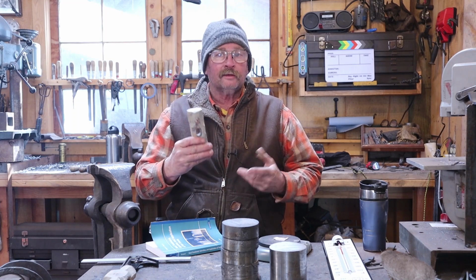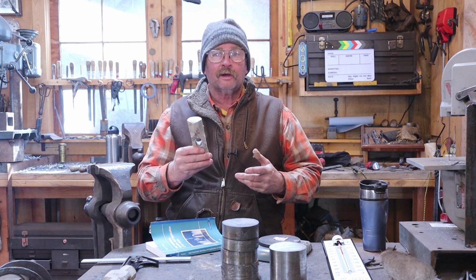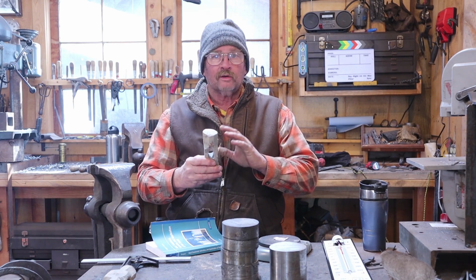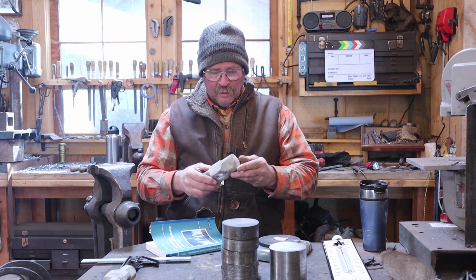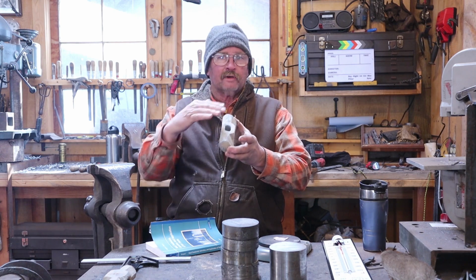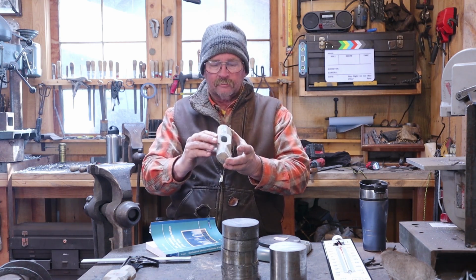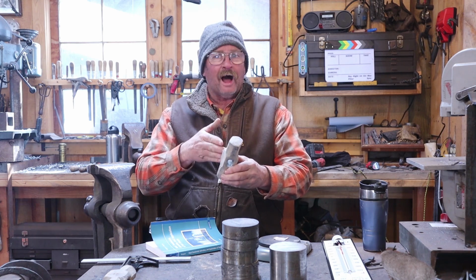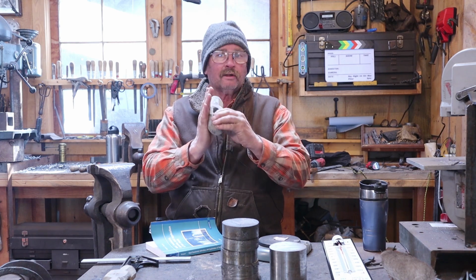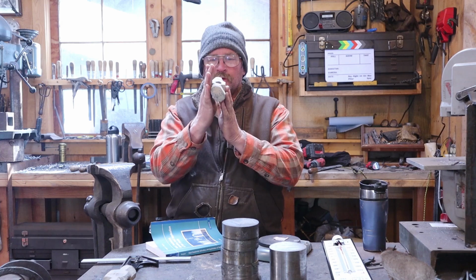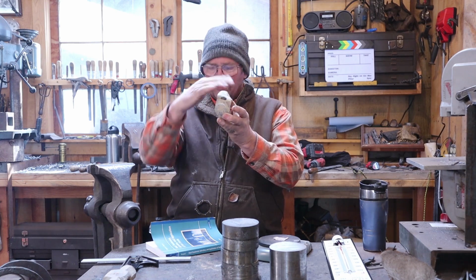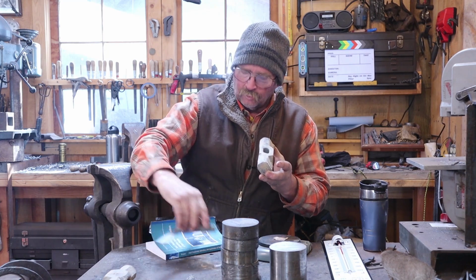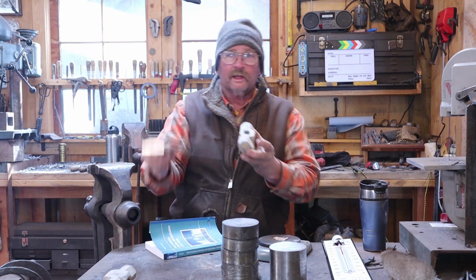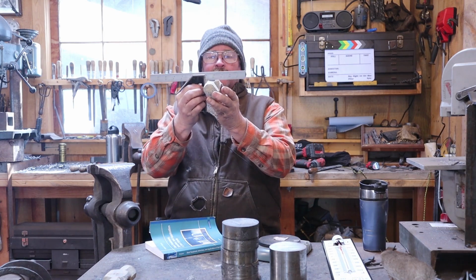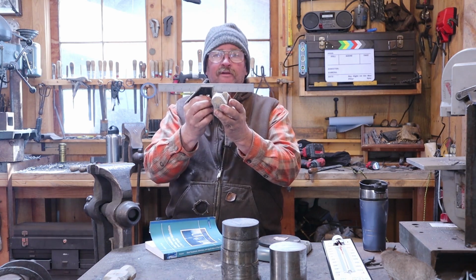Well, our hammerhead has cooled overnight. It's now ready to do a little bit of finish grinding on, get it in final shape. Looking at the little bit of an offset, the diamond we looked at yesterday, the eye runs straight and parallel with the sides. So the sides really aren't a problem. It's the top and the bottom that's just a little bit out of square, and it isn't really all that bad. This is about a 1/16 of an inch out of square.